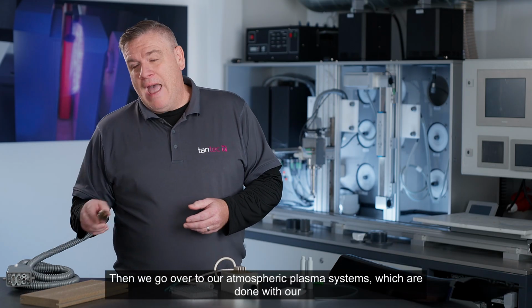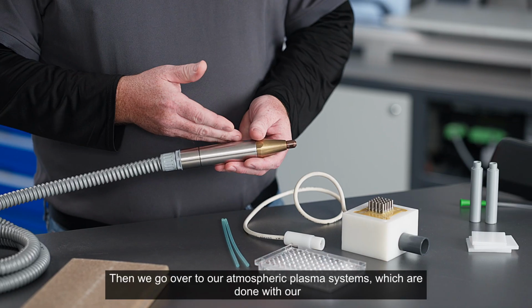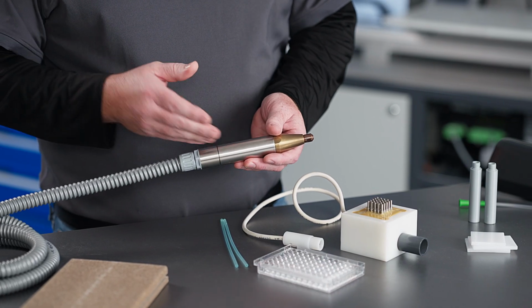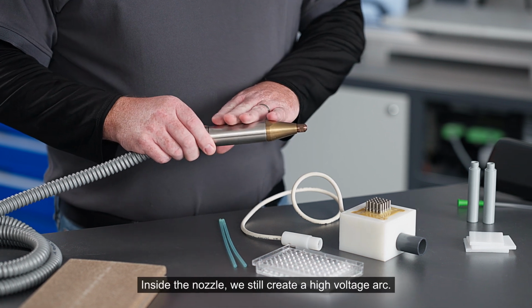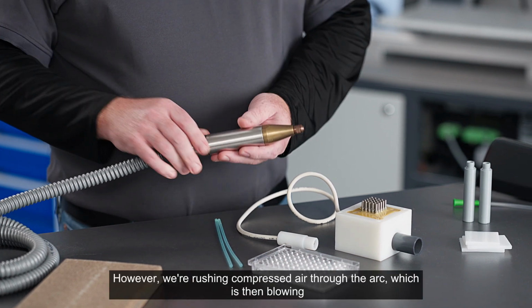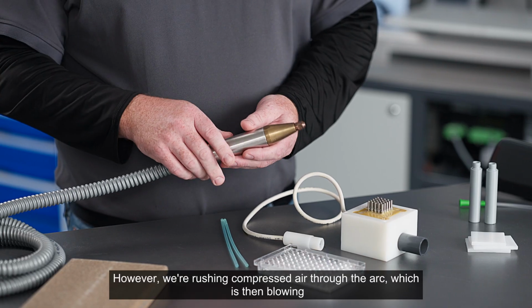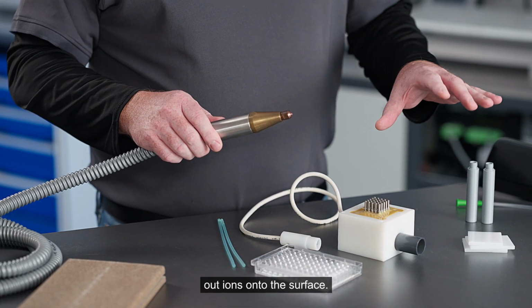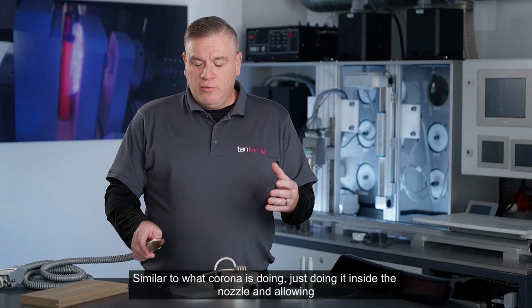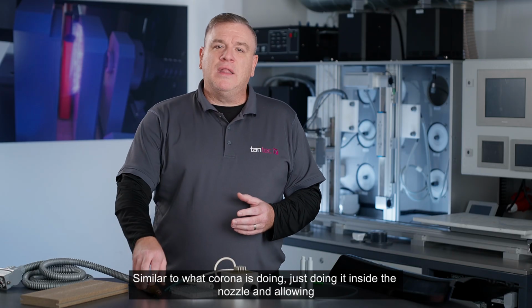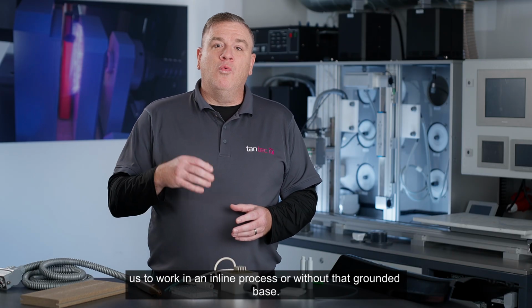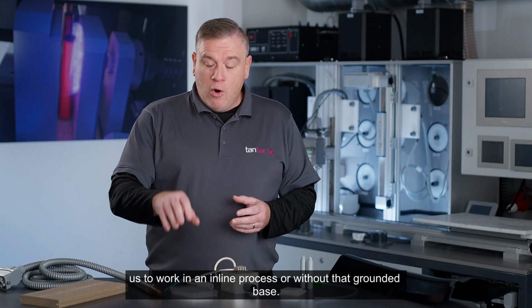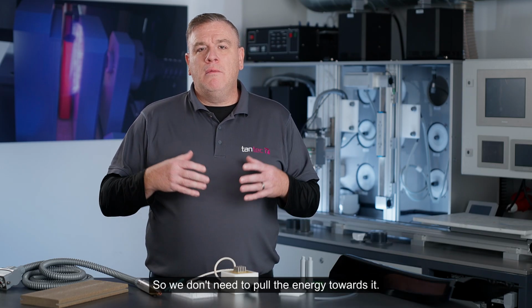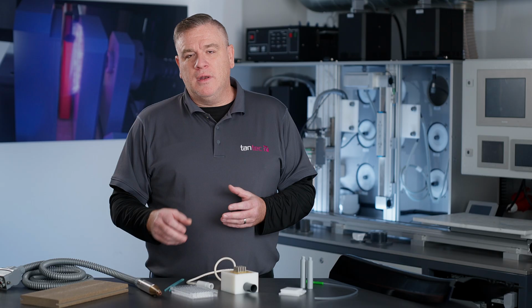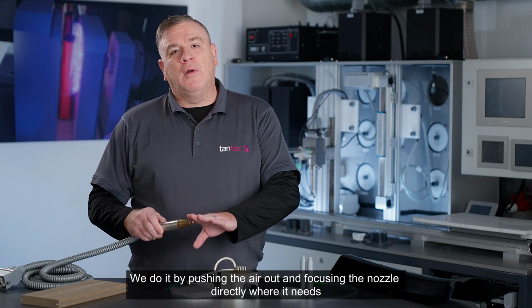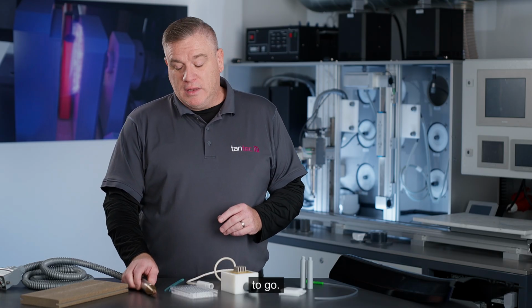Then we go over to our atmospheric plasma systems, which are done with our plasma nozzle system. Inside the nozzle, we still create a high voltage arc. However, we're rushing compressed air through the arc, which is then blowing out ions onto the surface. Similar to what corona is doing, just doing it inside the nozzle and allowing us to work in an inline process or without that grounded base. So we don't need to pull the energy towards it. We do it by pushing the air out and focusing the nozzle directly where it needs to go.